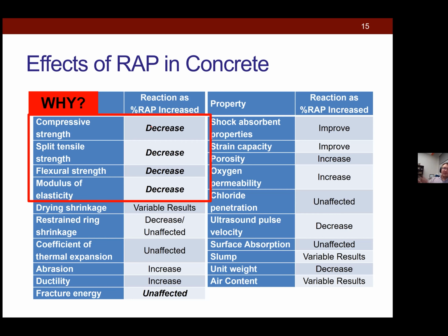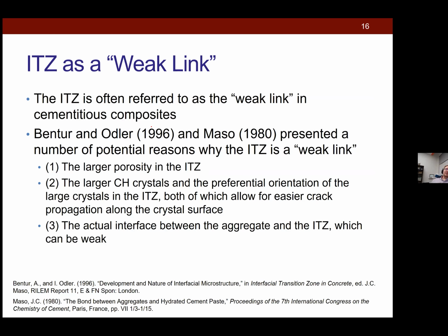All right, and I'm not showing that data because we just don't quite have the time. So you just have to take my word on it, or look up some papers, right? So we were finding that no matter what we kind of did to the binder, you can probably reduce the water cement ratio a bit, but it didn't have that great of an effect. So clearly something was going on with the microstructure. And so this is pretty much where my PhD work went, was trying to figure out why, microstructurally, asphalt is not playing nice with the cement binder.